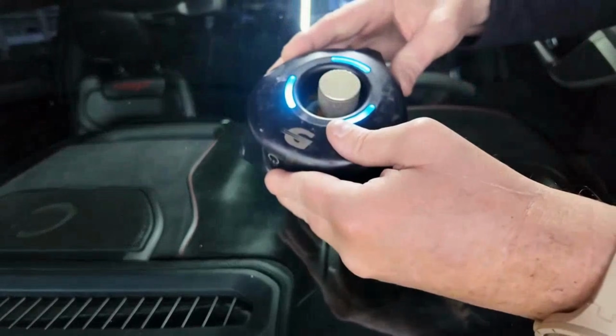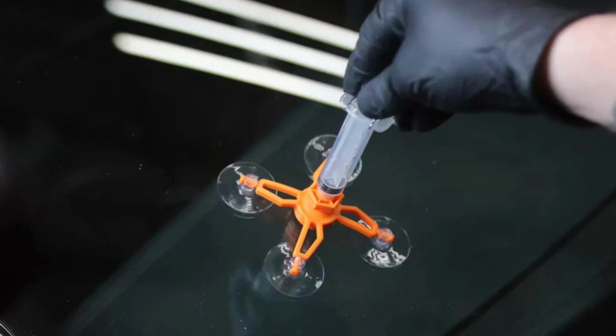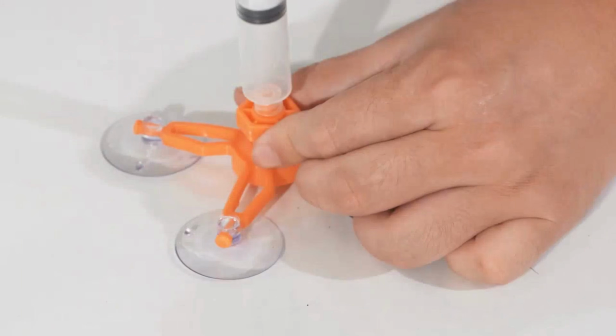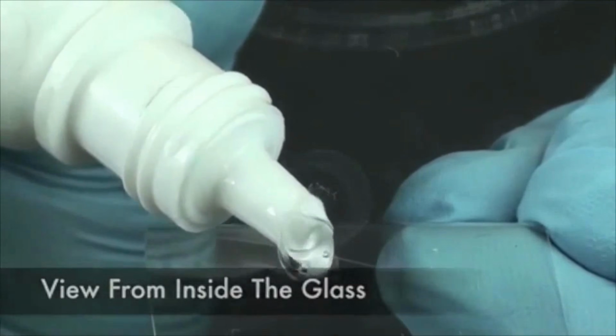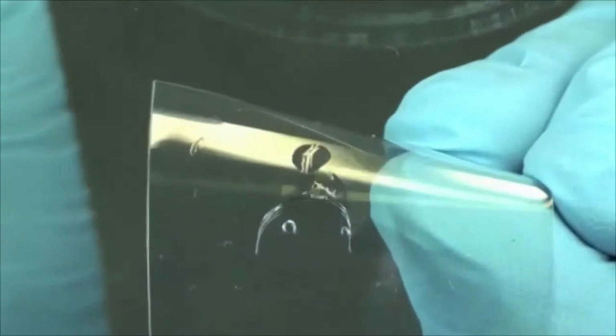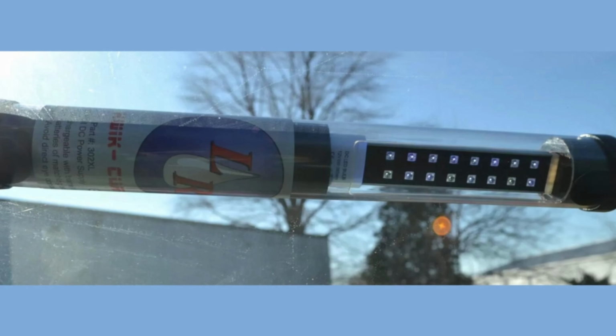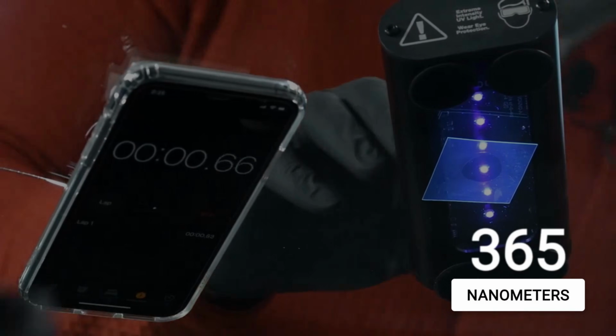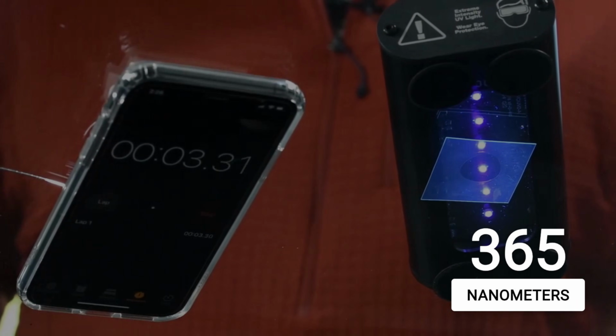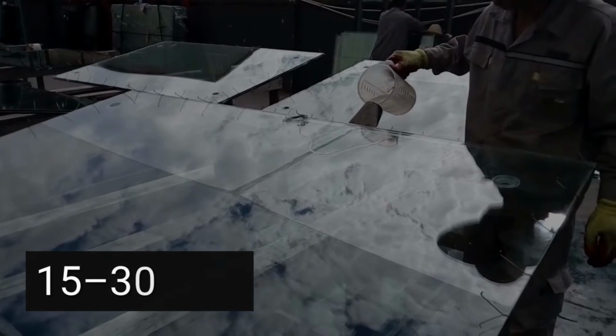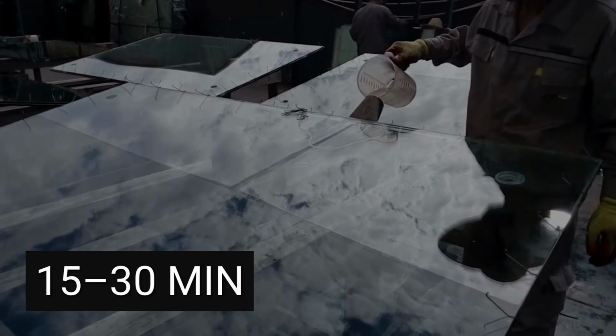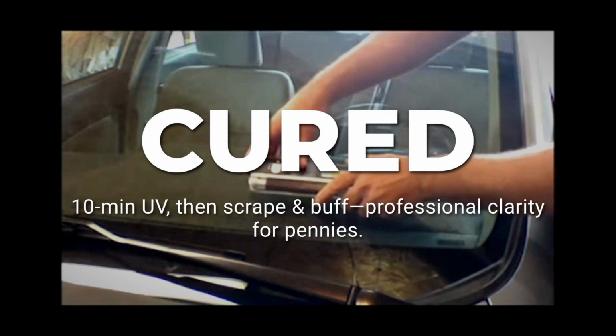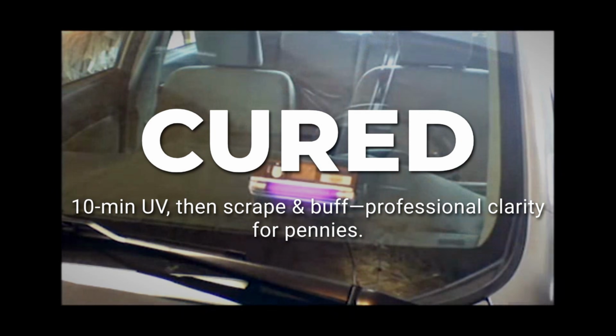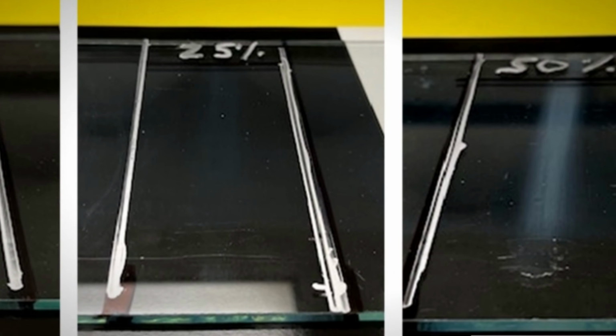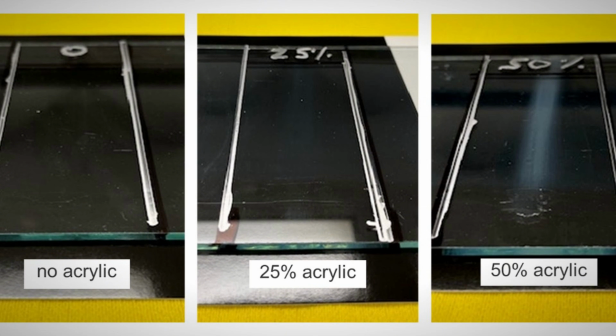Step 5. Cure with ultraviolet light. Once the resin has fully filled the crack, remove the syringe and the pedestal. Apply a thin curing strip, a small piece of clear film, over the resin. Move the vehicle into direct sunlight or use an ultraviolet curing lamp. The resin needs ultraviolet light at around 365 nanometers to polymerize. In direct sunlight, curing takes about 15 to 30 minutes. With a dedicated ultraviolet lamp, as little as 5 to 10 minutes. Do not rush this. Under-cured resin will remain soft and can fail over time.